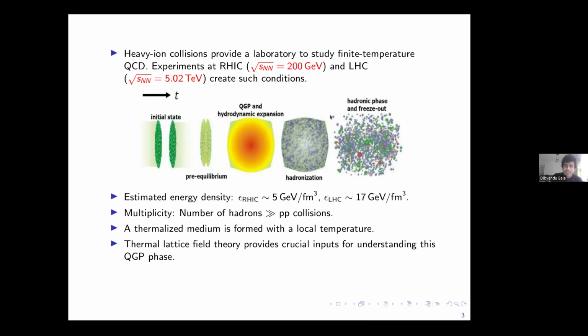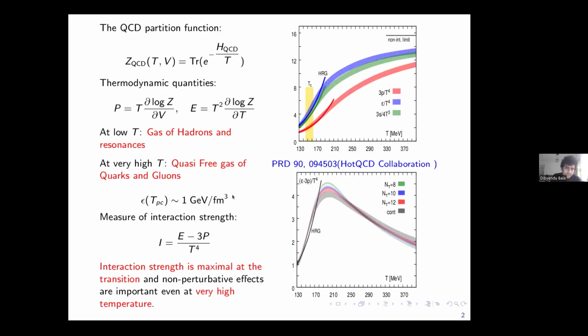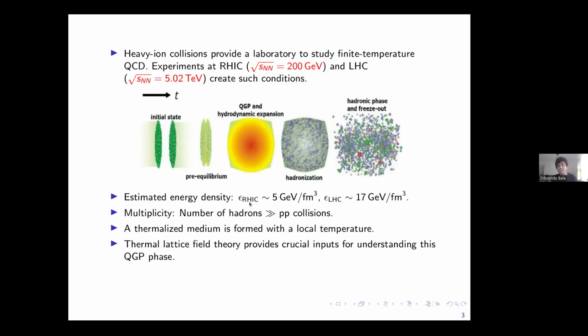So how do I study this system? From what is detected in the detector, first of all I have to ensure that there is a QGP. There is an estimate of the energy that can be calculated from the particles detected in the detector. It turns out that at RHIC the energy density produced by these collisions is about 5 GeV per Fermi cubed, and for LHC it's 17 GeV per Fermi cubed. As I showed there, QGP production requires only about 1 GeV per Fermi cubed. So this energy density is way above what is required for QGP production.